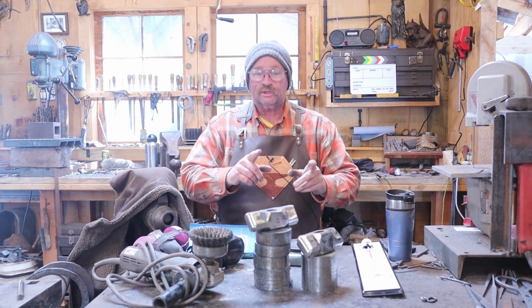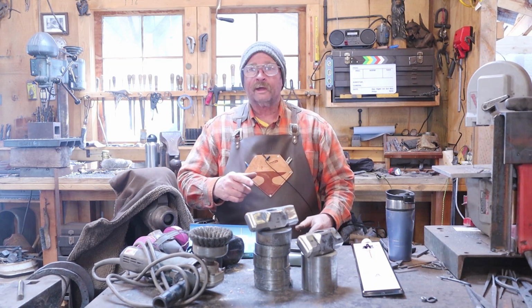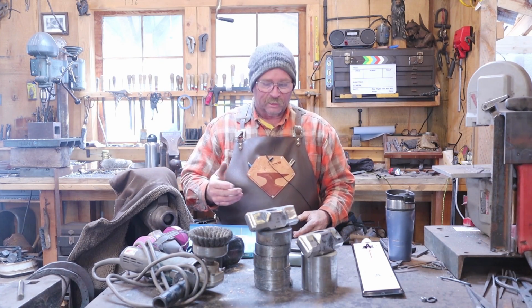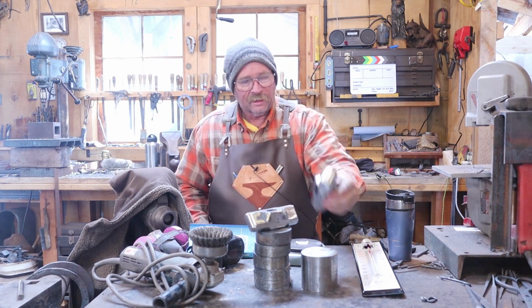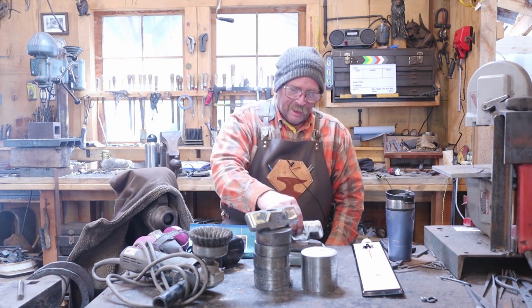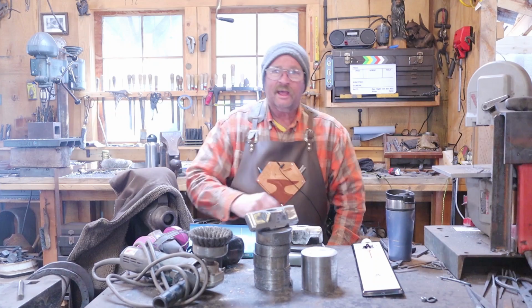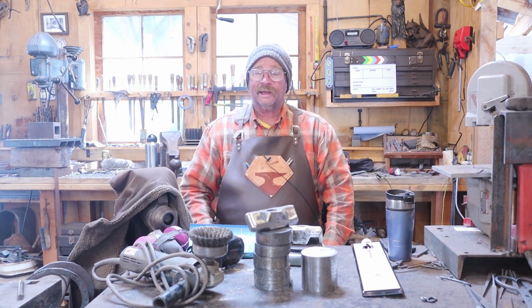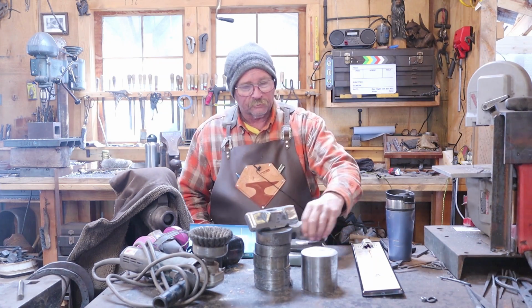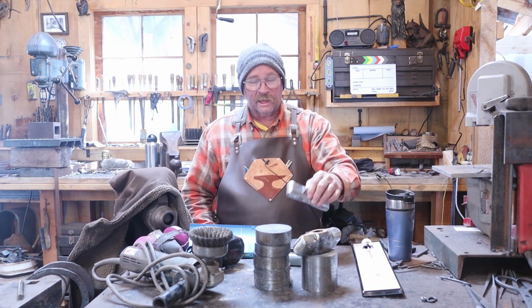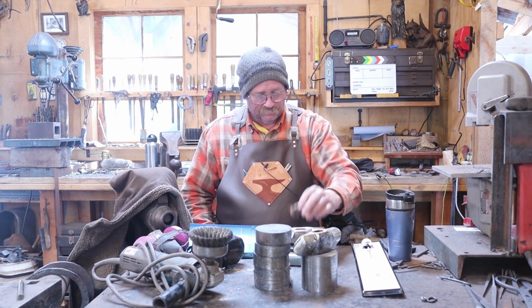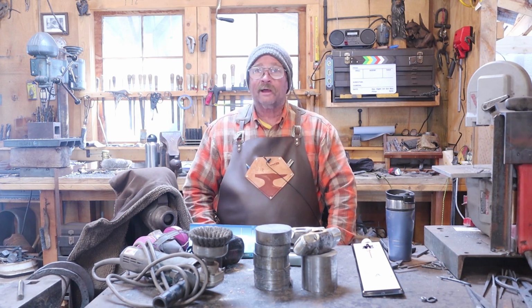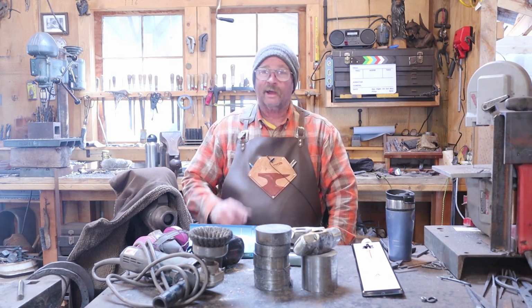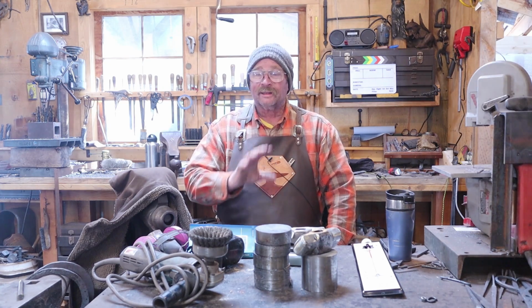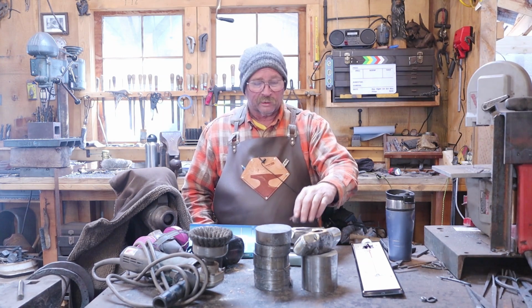Now I've actually made 2 of these hammers. One of them I did before the first video as kind of a test piece, and that's a little bit bigger one. After grinding, it weighs 3 pounds, 15 ounces, so almost 4 pounds. The smaller one that should weigh 3.5 pounds or 3 pounds, 8 ounces, weighs 3 pounds, 8.3 ounces. So after hardening, tempering, a little bit of polish, we're going to be right on the money with this one.